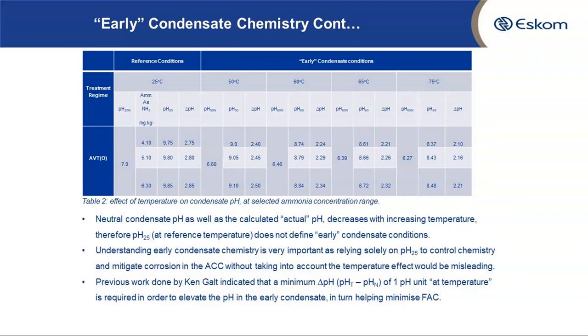Basically, this information tells us that it is not always the case that we should rely on information that is reported at standard temperature, because the chemistry at temperature will most likely be different depending on the species that are present in either water or steam. So it is important that one understands the condensate chemistry, as relying on the pH to control and mitigate the corrosion in the ACC without taking into account the temperature effect is not going to be effective.